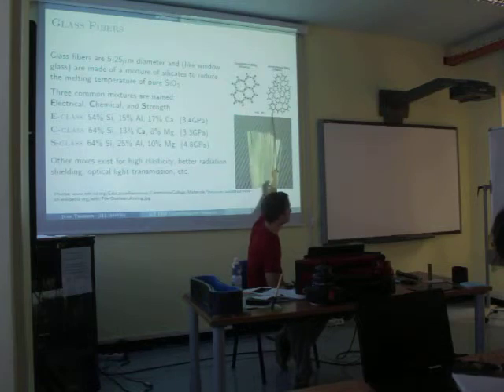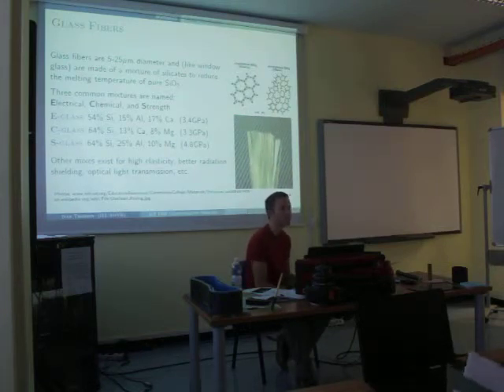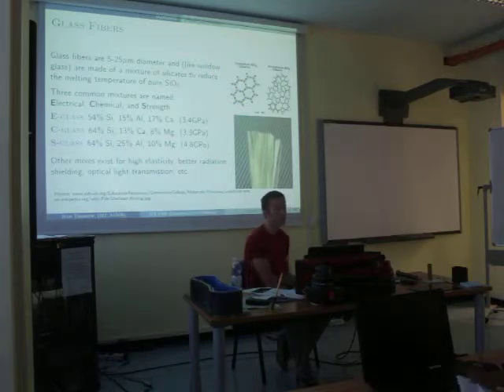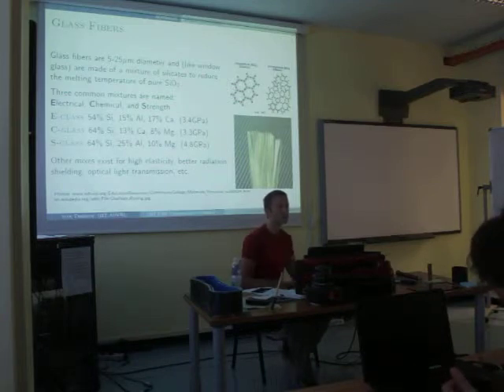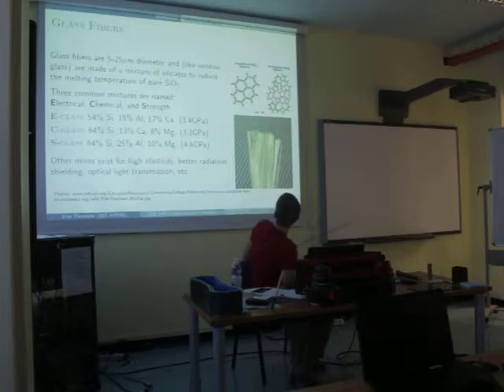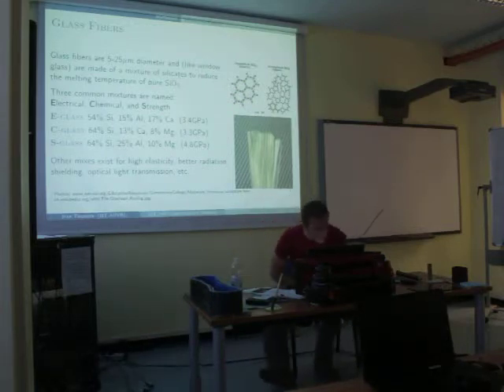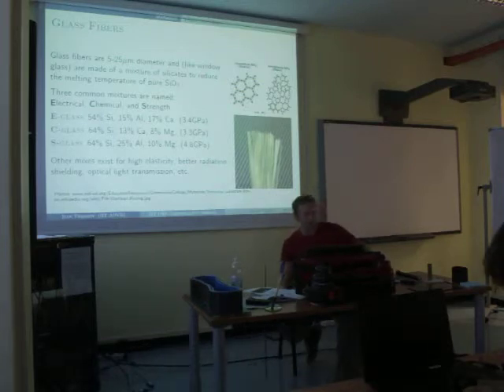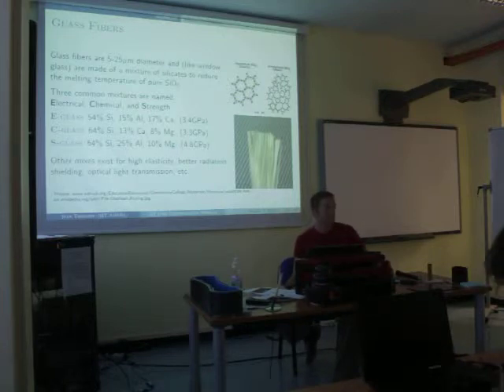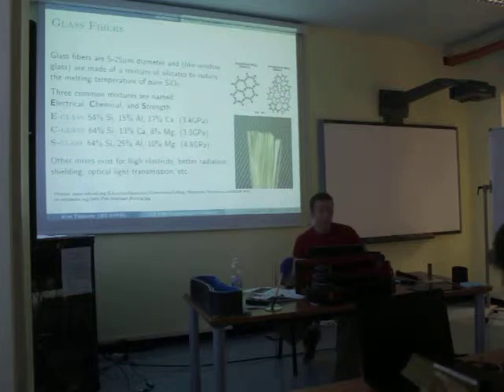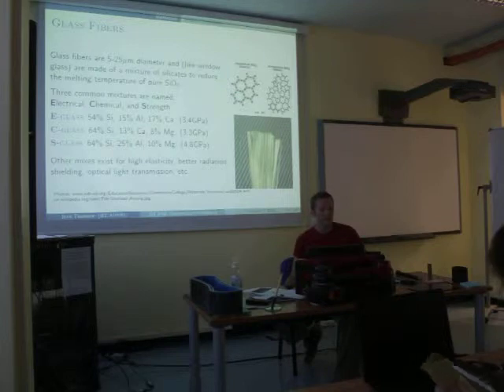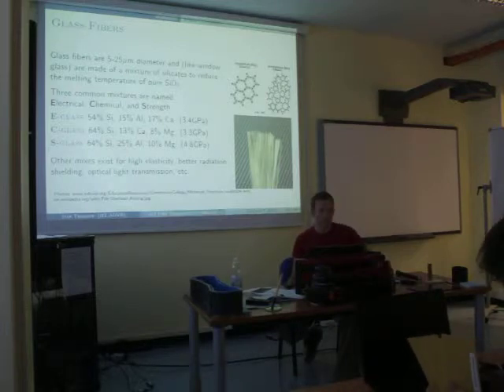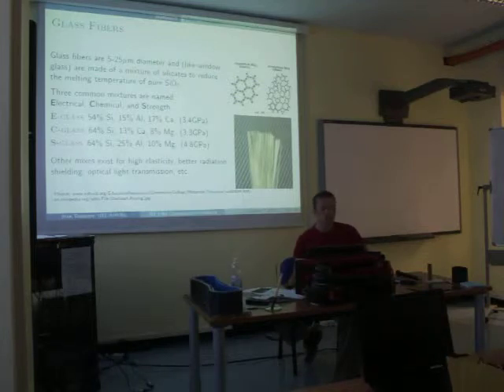I don't know much about chemistry, but I think some of these molecular diagrams are interesting because the fundamental material strength of all these materials, of the glues, of the fibers, everything relies on long molecular chains with some cross-linking between the molecular chains to create a strong material. So the three types of glass that are commonly used are called E-glass, C-glass, and S-glass. Most people are going to be using E-glass, which is the most common. You buy that at the boat store or anything like that. Or S-glass for strength. E-glass is electrical, C is chemical, and S is for strength. The S-glasses are about maybe 20%, 30% stronger than the E-glasses, and are often used for structural application. You can also make different blends of glasses if you want, which have higher elasticity, radiation shielding, sometimes they use lead in them. They have different glass fibers for fiber optics and light transmission.